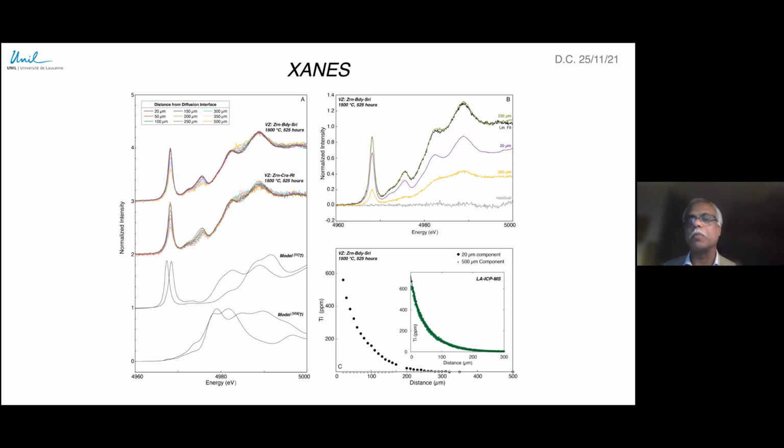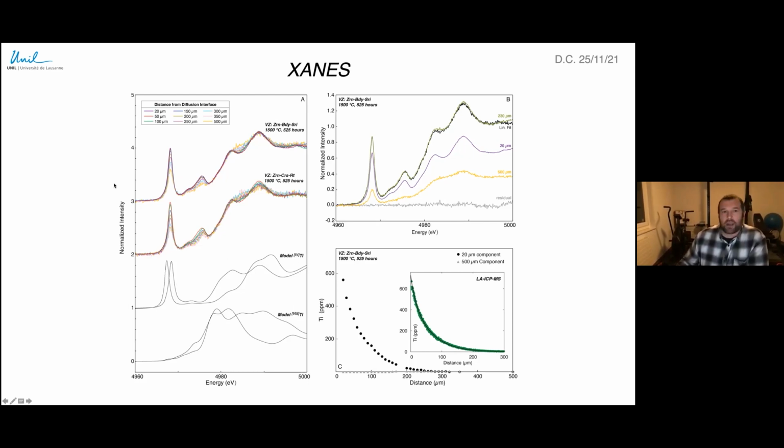Well, we were just talking about that. Yeah, no, I don't think so. On the bottom here, we have the model spectra we should see if we're dealing with 8-coordinated titanium, which is what we would expect if it was in the zirconium site. And we don't see that. We see the very important features of the model 4-coordinated titanium. So I'm quite confident it's either sitting on the silicon site or the interstitial site. My best guess would be that it sits on the interstitial sites.